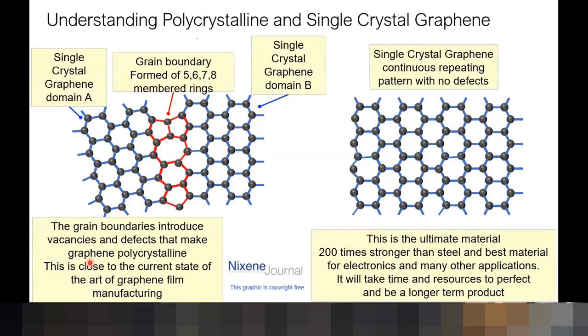Next slide, please, Mike. You recognize the term polycrystalline now, and that piece of graphene that you saw on the copper foil was polycrystalline graphene, where the domains have grown together, and then you get these slight disconnects where they don't quite connect up properly. These red lines on that image show you where you get 5, 6, 7 and more membered rings. Now that's fine for quite a lot of applications, but for extreme applications, we're after perfect single crystal graphene, which is this chicken wire with no defects whatsoever. And that has already been made, and we'll talk about that in a minute.